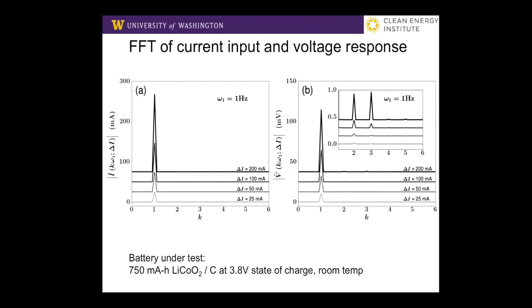We see that the magnitude of the Fourier coefficient rises linearly with the delta I, the modulation potential. That's what we'd expect. Coming out is the Fourier spectrum of the voltage for this battery. And we can see at the first harmonic, K equals 1, we have this roughly linearly growing peak. By the way, we've just offset them so that you can see the peaks. It's not a natural offset. They all have 0 baselines.